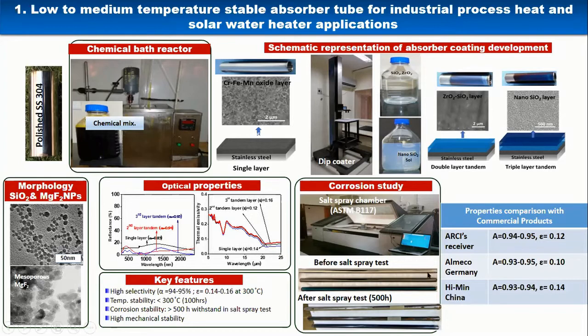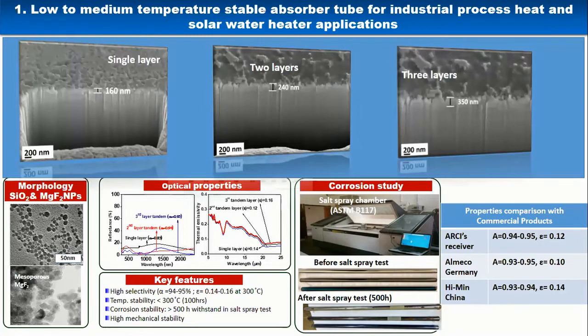Right now Almeco is developing a PVD based coating, and our coating properties are almost equivalent to the commercial one. Recently, a Chinese company is also developing a PVD based coating, so the property is almost equivalent to the commercial one. Here you can see the first single layer thickness that we measured is around 160. Usually, if you want more optical properties in a wider range from 300 to 2500, we need a multi-layer.